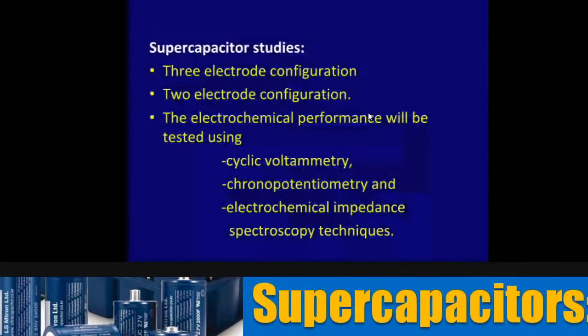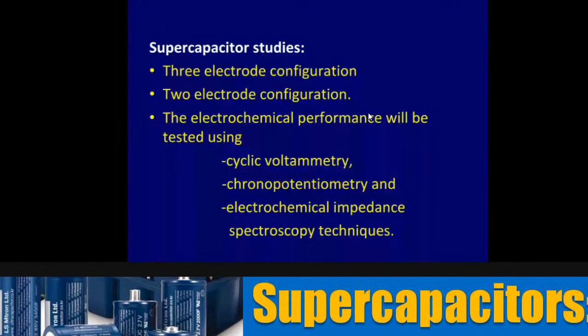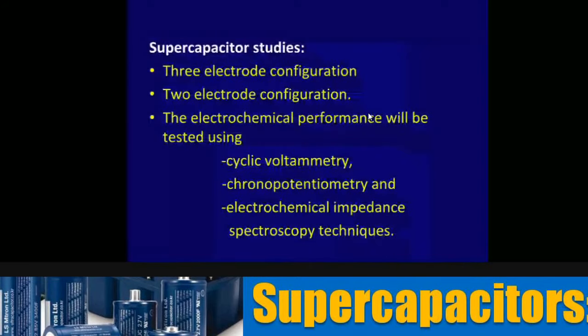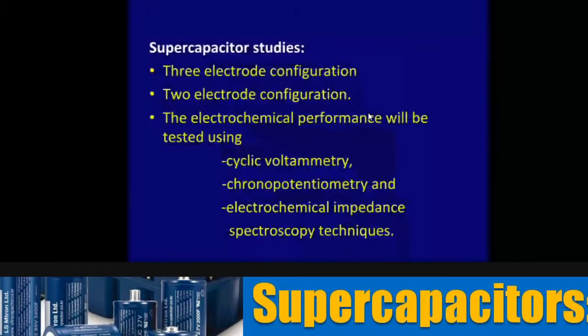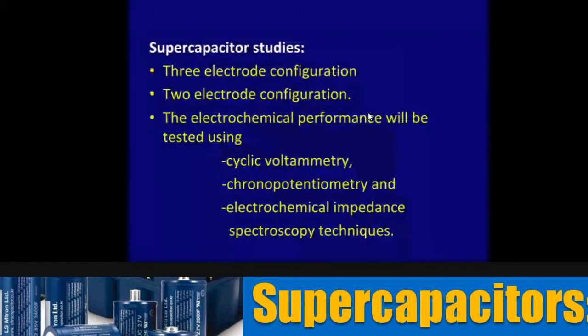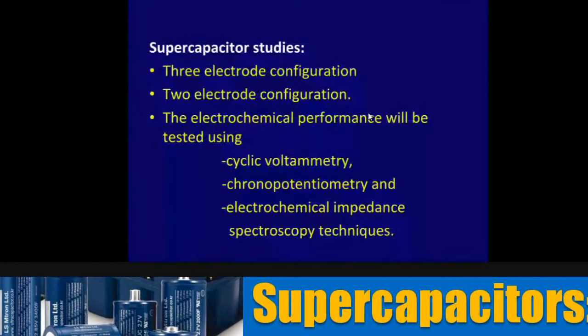And when we go to capacitors, we try to use a 3-electrode configuration. That means we use the material as the working electrode. There will be a counter electrode, and because we are using 2 electrodes, a 3rd electrode is used as a reference electrode. Thereby we will be able to make the measurement. We also make 2-electrode systems because these 2-electrode systems are the ones which are practically important. The reason why I say is, in a 3-electrode configuration, we may see the performance to be 1000 farad per gram. But the moment you make a real life 2-electrode configuration, you will see that the capacity drops down to 50 to 100 farad per gram.